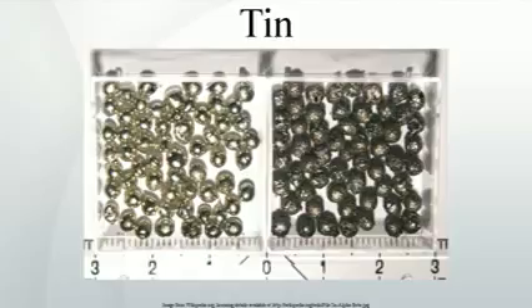Commercial grades of tin, 99.8%, resist transformation because of the inhibiting effect of the small amounts of bismuth, antimony, lead and silver present as impurities. Alloying elements such as copper, antimony, bismuth, cadmium and silver increase its hardness. Tin tends rather easily to form hard, brittle intermetallic phases, which are often undesirable. It does not form wide solid solution ranges in other metals in general, and there are few elements that have appreciable solid solubility in tin. Simple eutectic systems, however, occur with bismuth, gallium, lead, thallium and zinc.